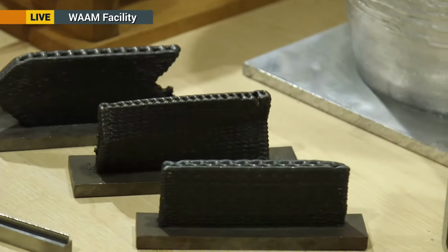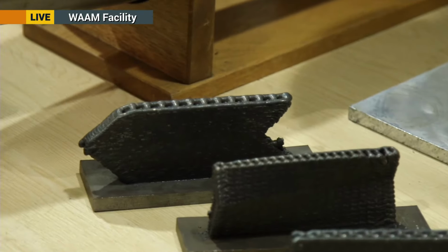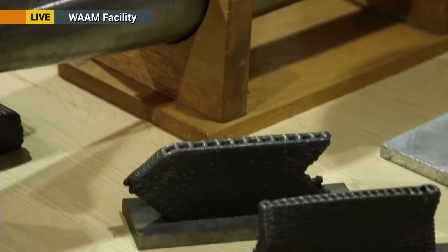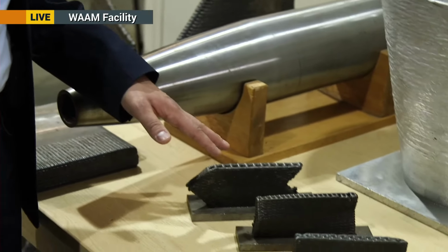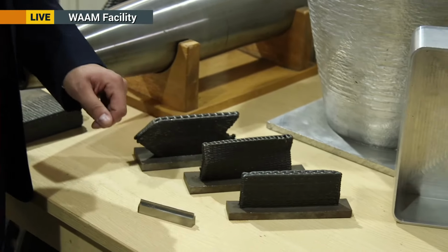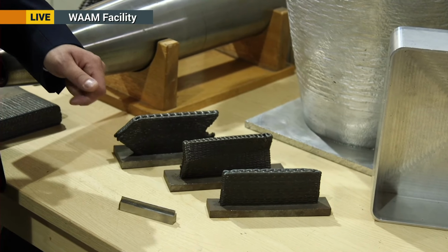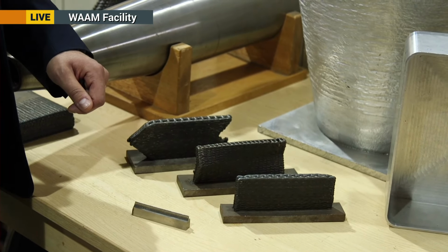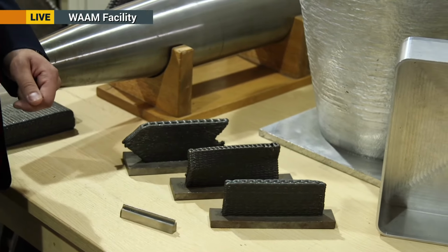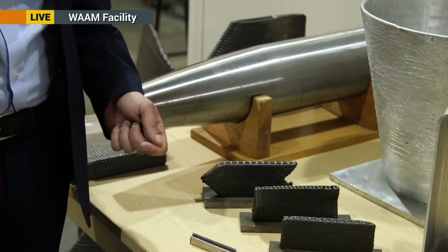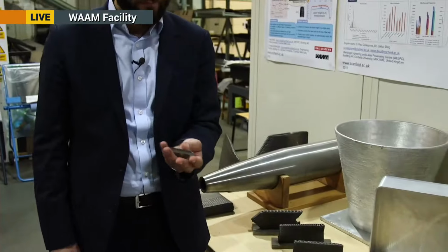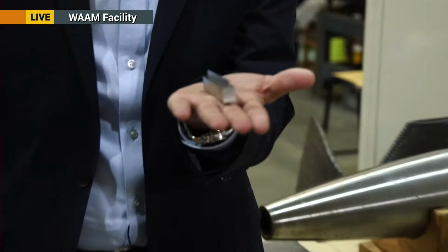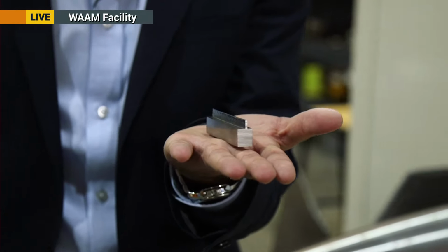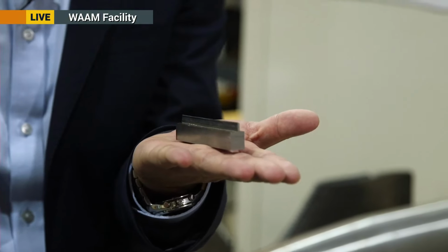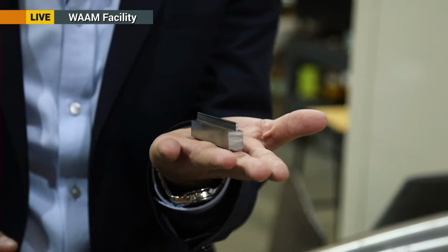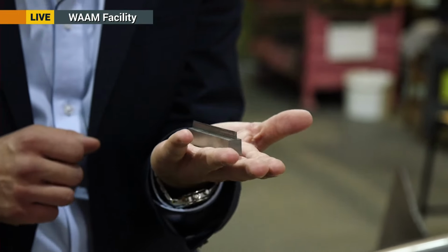And then finally, in terms of going forward, looking at how we can expand the geometrical capability of this process, we've been working very recently on dies for automotive application. This in particular is for the press forming of the A, B, and C pillar of your car chassis, as well as using other heat sources, like in this case, where we can deposit using a laser instead of an arc, and we can deposit much thinner structures, which crucially do not require any finish machining after they've been deposited.